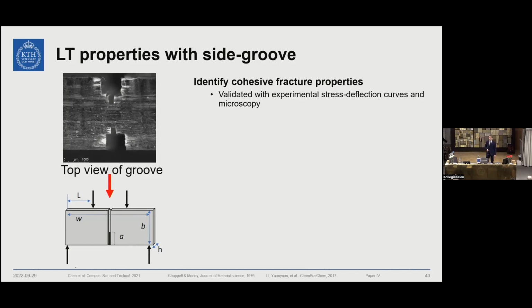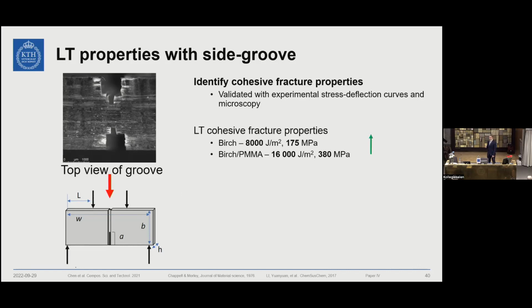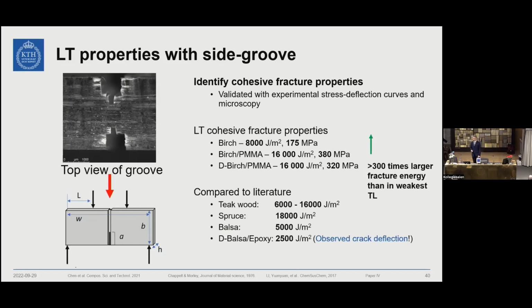By using cohesive models, we can identify the properties. We can see that by adding a polymer, we have a drastic increase in fracture energy, and also the strength. During the delignification, there is not much difference in fracture energy, some difference in the cohesive strength. But more importantly, comparing this with the weakest direction, it is about 300 times larger, which is quite amazing.